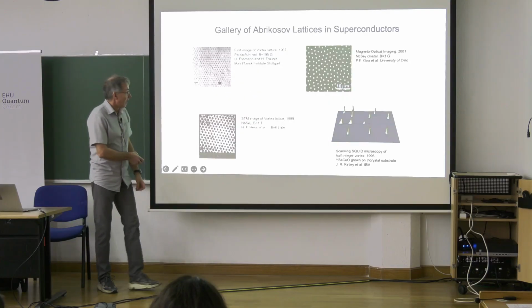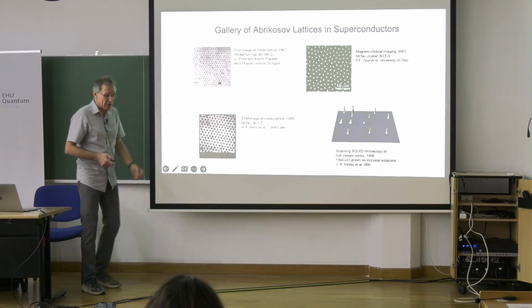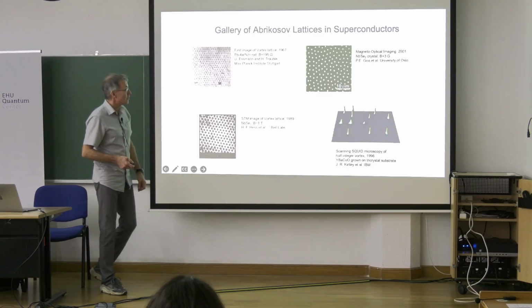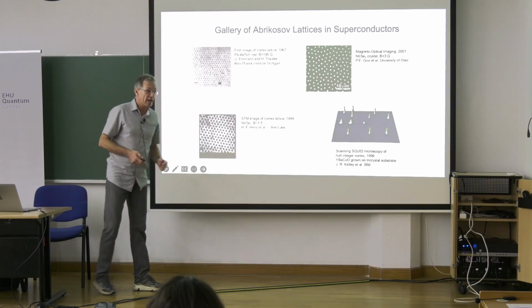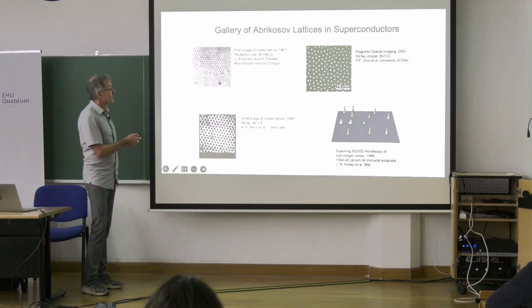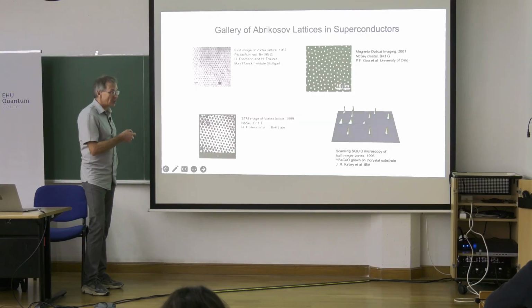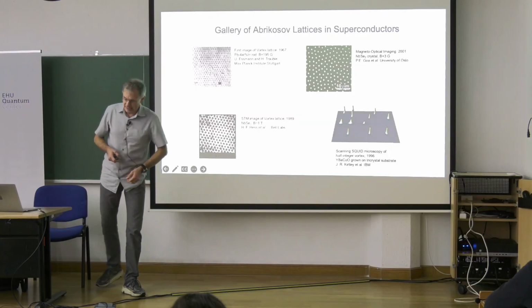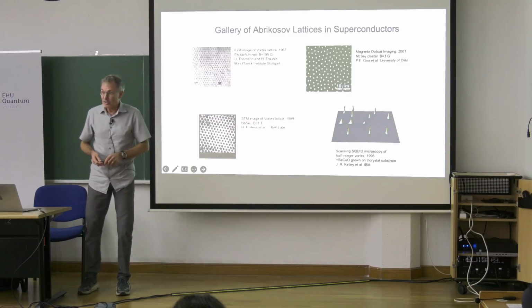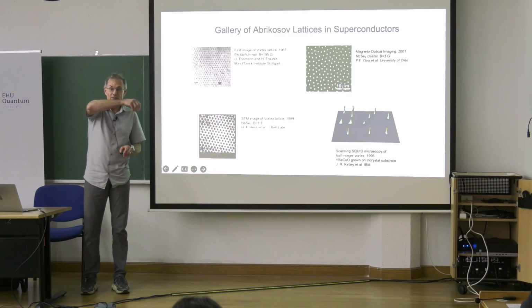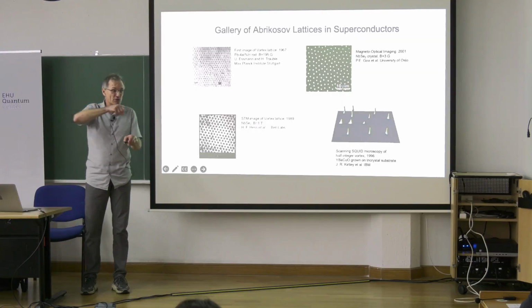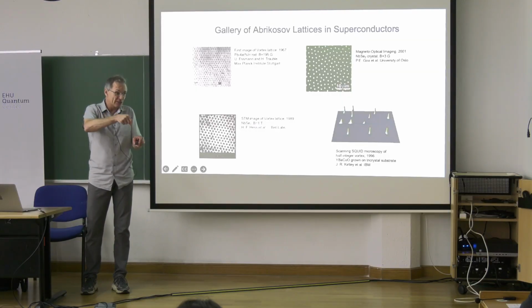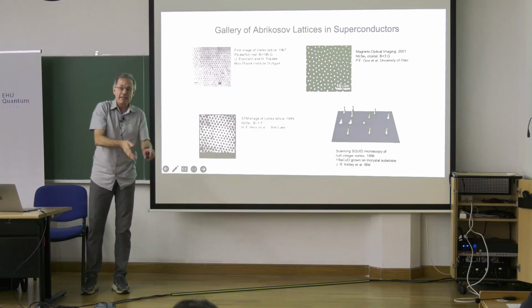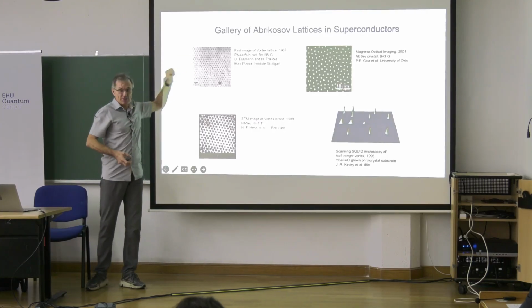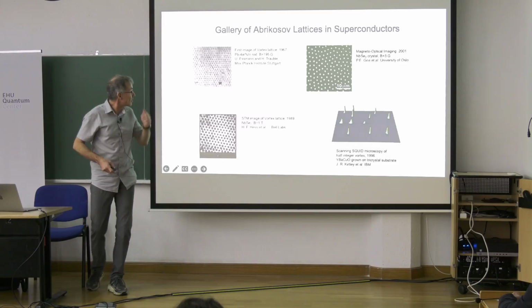So you can visualize this, see these vortices, almost with the naked eye, with different techniques. The first was an observation with a rather funny technique, which again is like a kindergarten type of technique. You take magnetic powder, you put it on the surface of your sample, and the magnetic particles are attracted to the place where the gradient of magnetic field is, and then you see it. So that's called magnetic decoration.